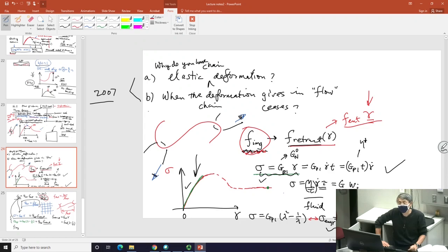I just said that the reason this gripping force is finite is because molecules performing their Brownian motion can relax. We'll get to the formula for this at some point in the near future, how to write this down. But basically, I may lose my ability to provide the uncrossability since my chains are all moving.